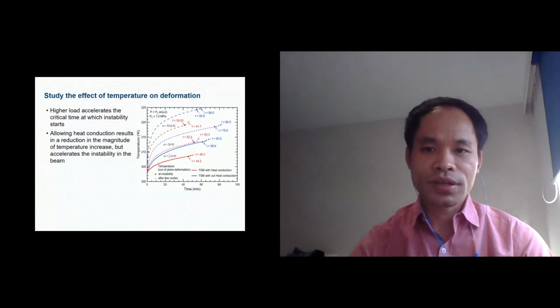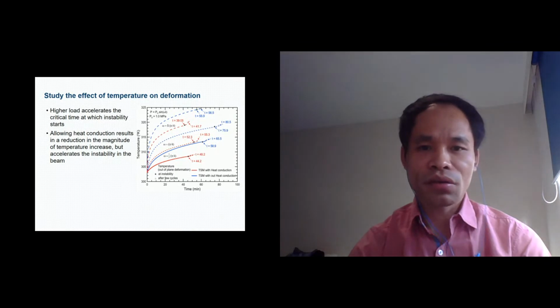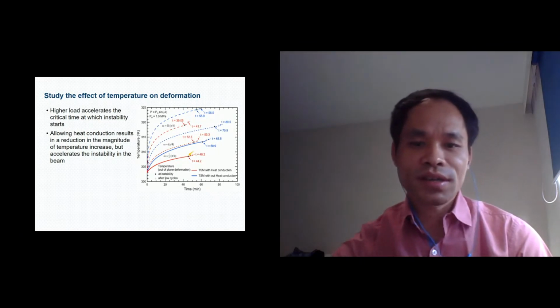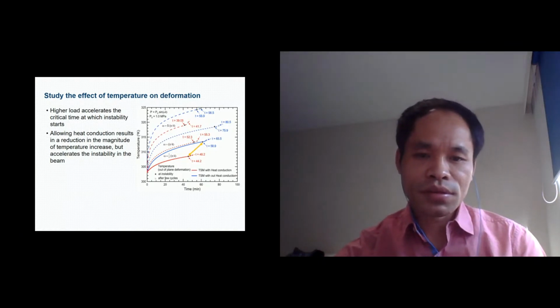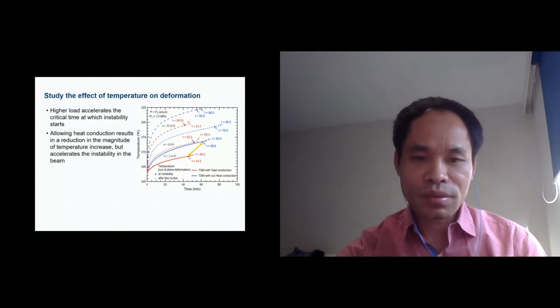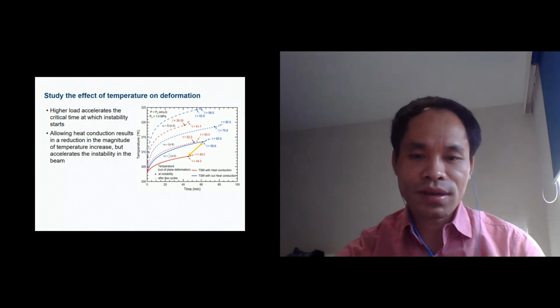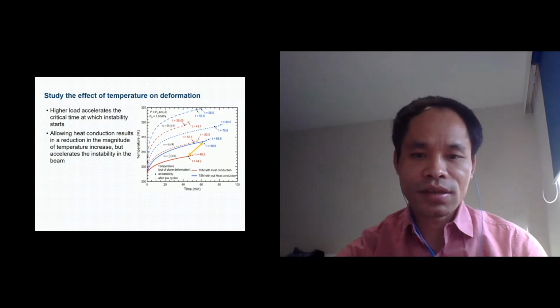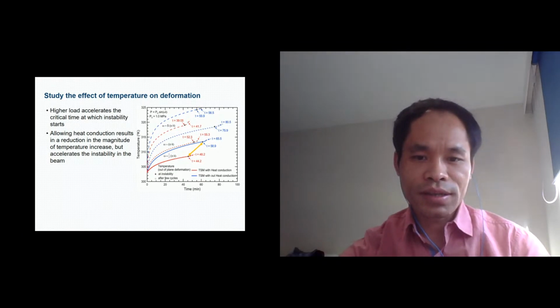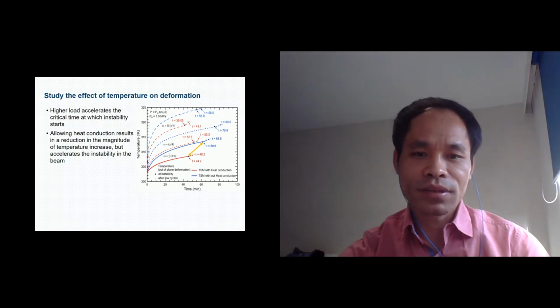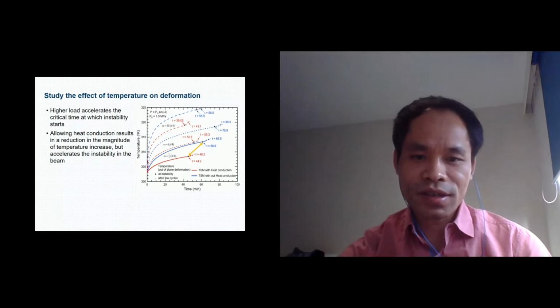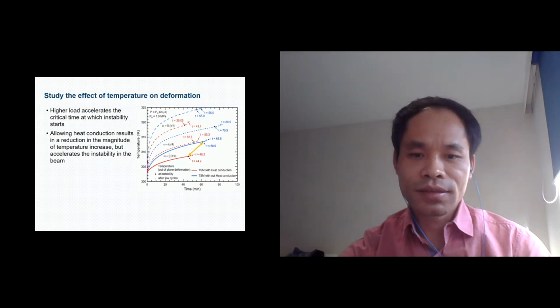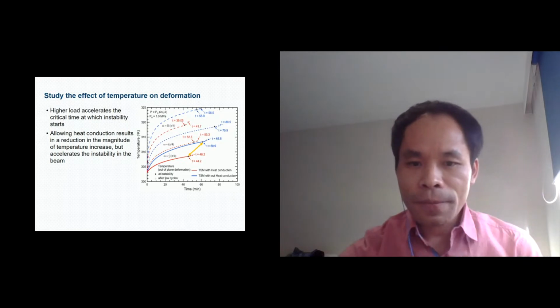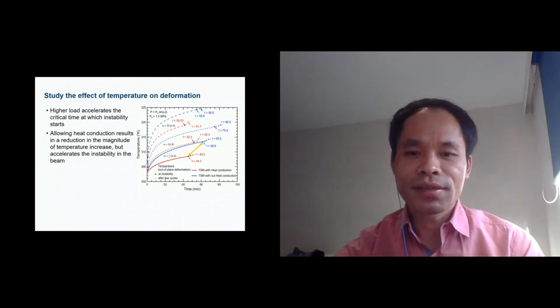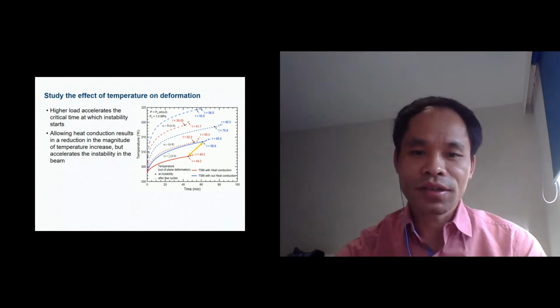Moving forward, I want to mention that temperature also has an impact on the deformation of microstructures. In this research, they conducted experiments on polymer beams. The instability of the matrix occurs for different heating temperatures, and they considered that when you consider temperature, you should also consider thermal properties, like heat conduction and non-heat conduction. The red line indicates heat conduction, and the blue line indicates without heat conduction.